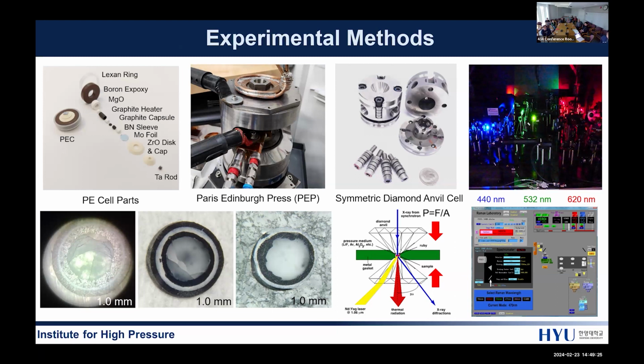I loaded these samples into the diamond anvil cell under non-hydrostatic conditions, and then conducted the Raman measurement at pressures ranging from ambient to 20 gigapascal using the blue, green, and red lasers. Notably, measurement with the green laser exhibits the highest resolution.